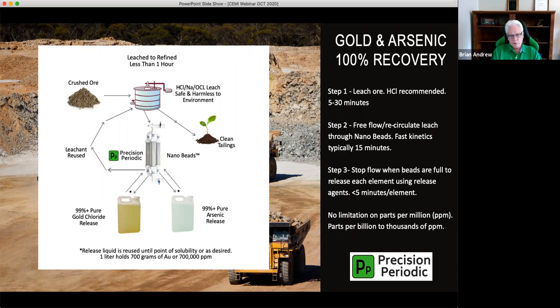And the particular system overseas, we're going to run about 1,000 ounces of gold a day. And it's the size of 2 containers, as opposed to across the road, there's a classic cyanide plant, which is about 3 city blocks and has a retention time of 7 weeks. And we do that with no ponds, no wasted liquor. And we actually start the process and run it with seawater. We don't even need pure water to run it. And then we recycle the water using another filter and good old desalination using the sun.